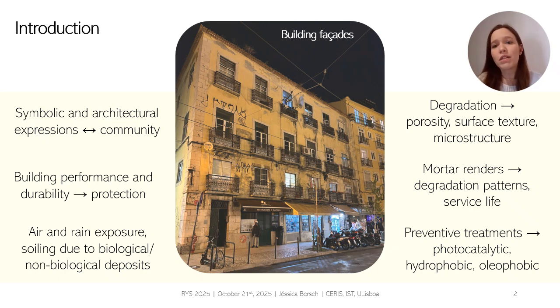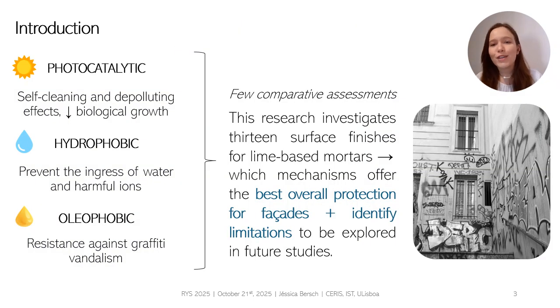Among the most noteworthy treatments we may have are photocatalytic, hydrophobic, and oleophobic coatings. Photocatalytic coatings normally include titanium dioxide in their composition. By combining chemical reactions with superhydrophilicity, they may provide self-cleaning and depolluting effects to facades, further reducing biological growth. Hydrophobic coatings are normally composed of silanes or siloxanes, and they prevent the ingress of water and harmful ions. Oleophobic coatings offer a barrier that provides resistance against graffiti vandalism.